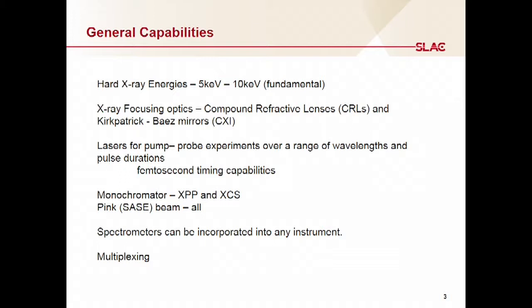Along with the laser for pump probe, there's femtosecond timing capabilities. Because the SASE beam certainly jitters timing-wise, so it's plus or minus 100 femtoseconds because of the SASE, the spontaneous emission capabilities. We really need femtosecond timing capabilities to see exactly what the time delay is between your optical laser and your X-ray pulse, which is coming in. And so that is available for all of them.